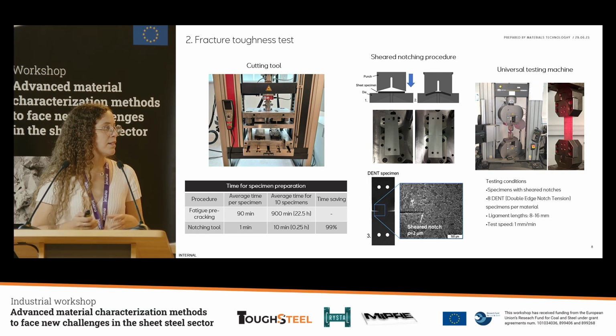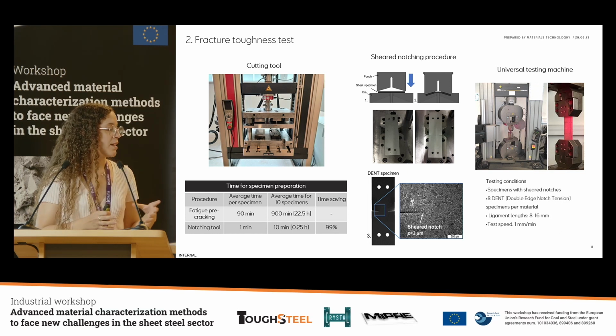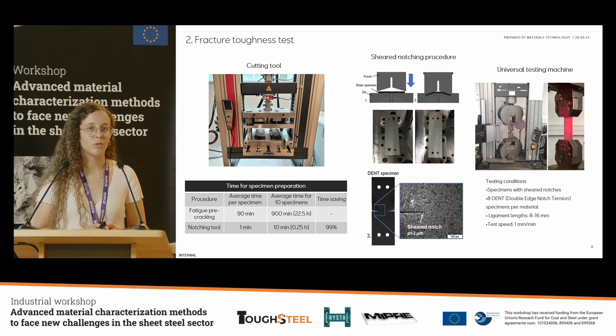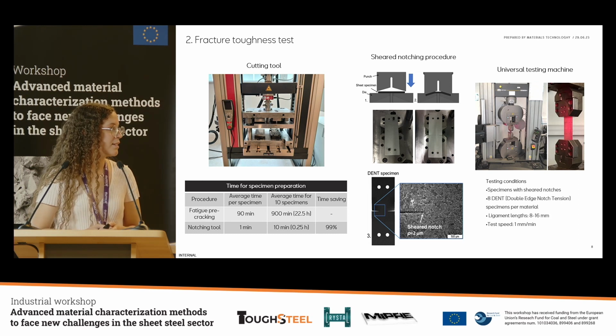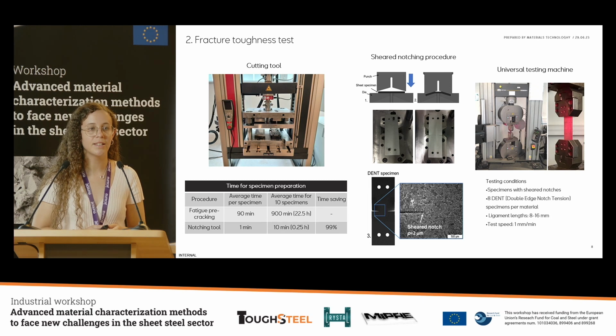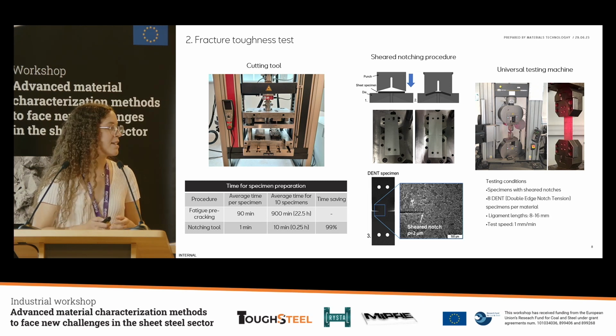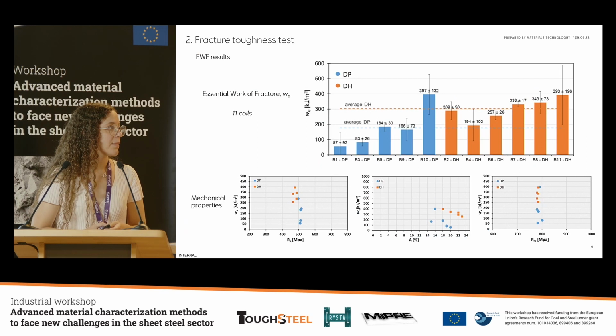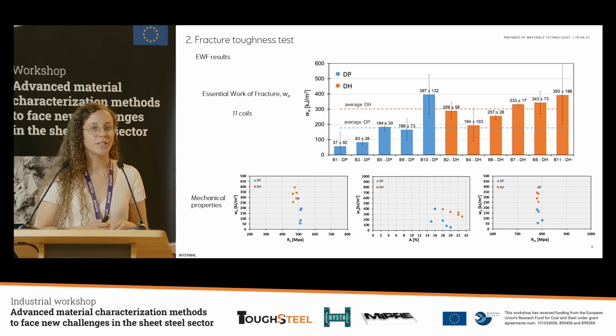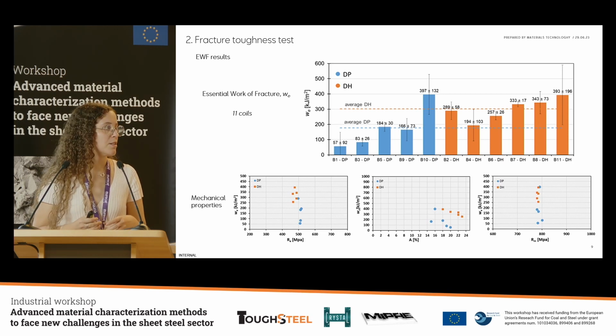Then, with all the experimental part, we gave the tool to SEAT. They installed it in their facilities, and they started testing all the materials. They tested 11 coils of material, which was quite a lot of material, so it was not possible to do it with the fatigue pre-cracks and get fast results. So it needed something implementable in the industry.